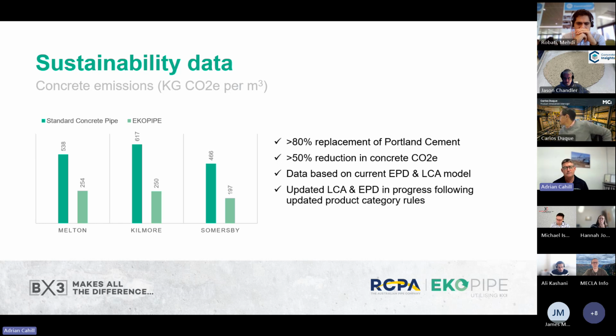But look, the results speak for themselves. The fact that we're able to replace more than 80% of the Portland cement with SCMs directly leads to a greater than 50% reduction in the embodied carbon for the concrete itself. When it comes to the finished pipe, there's a little bit more nuance, because you've obviously got the reinforcing steel that goes into that pipe.